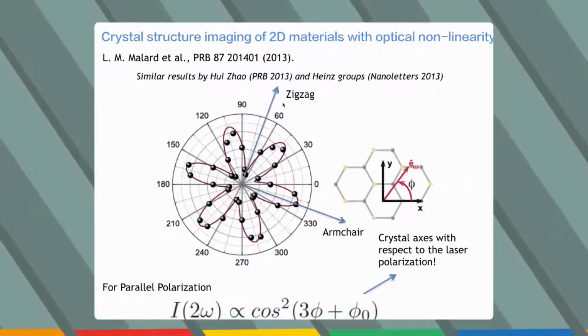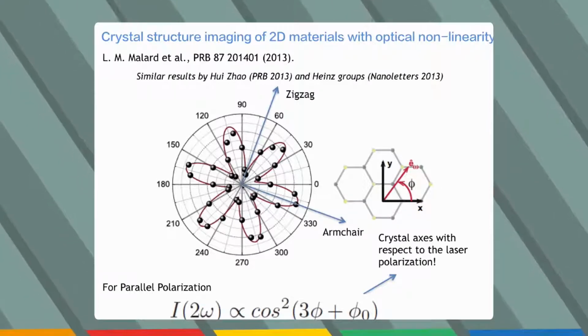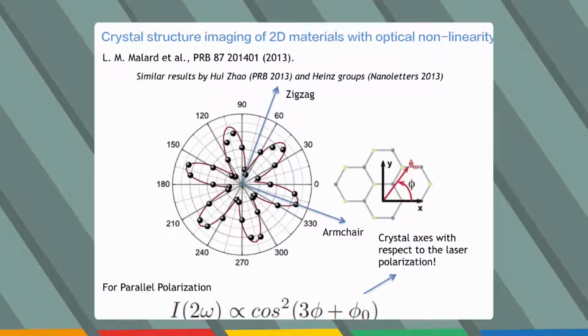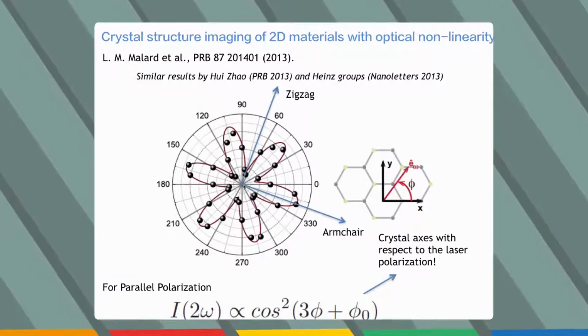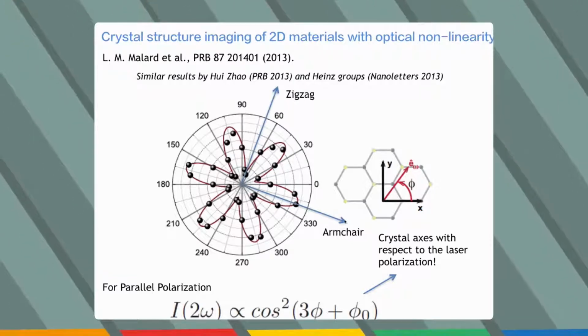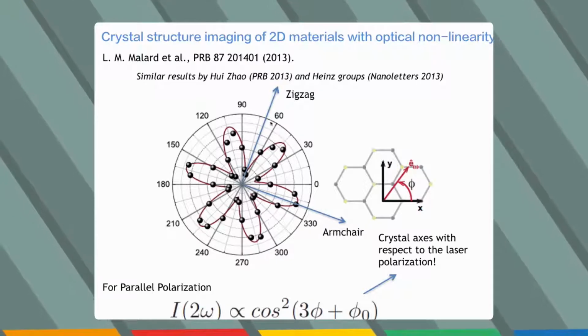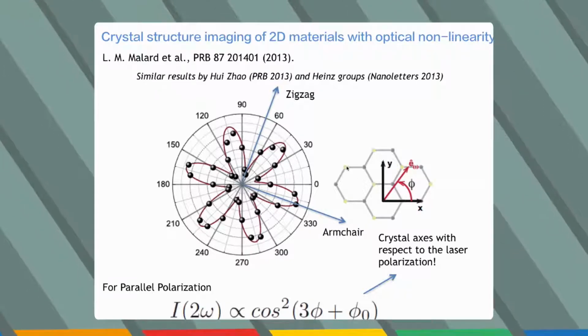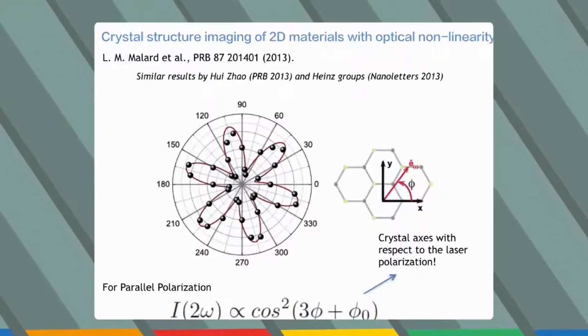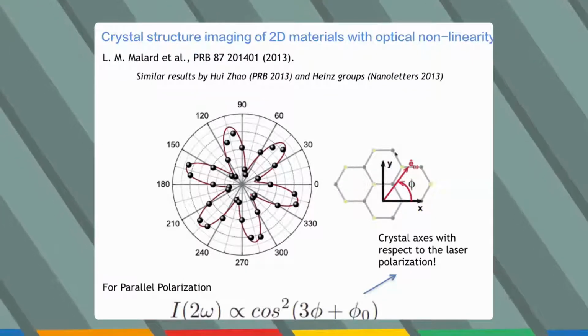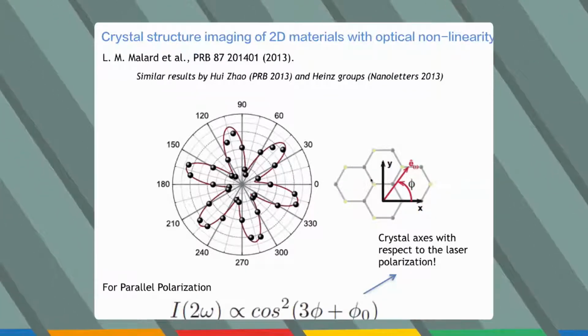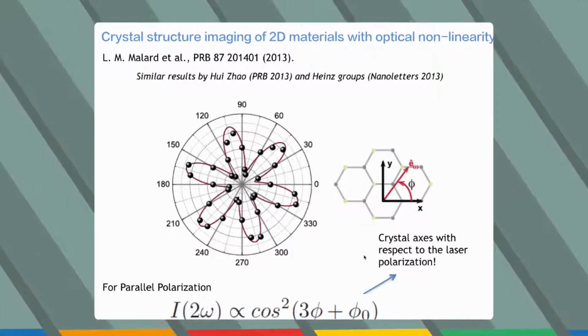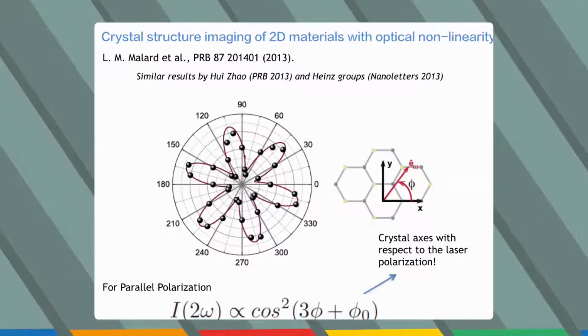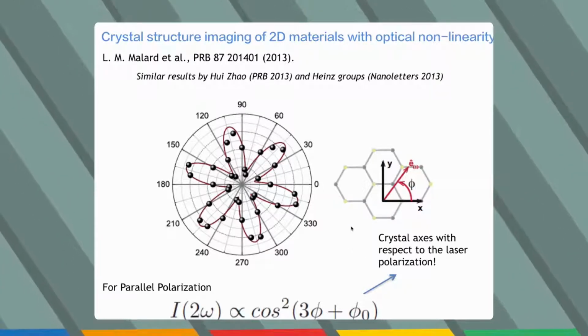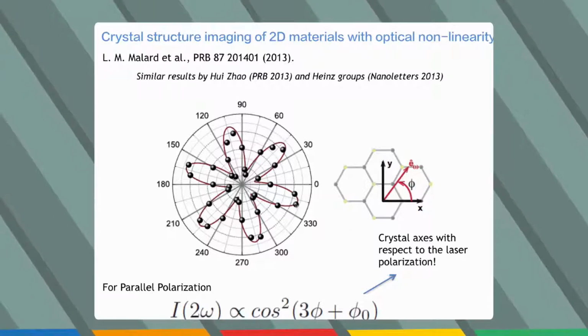And moreover, we can determine the crystal direction by doing this type of experiment. We know that this is going to be the armchair direction of the crystal, and this is the zigzag direction. So this is the armchair direction, the X direction, and the Y direction is the zigzag direction. So now we have a tool to determine the orientation angle of the sample.